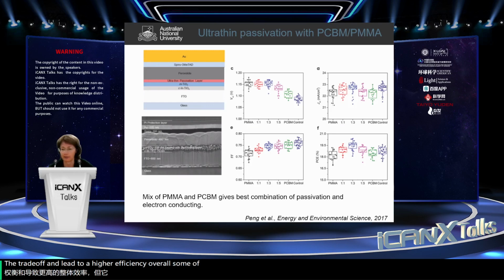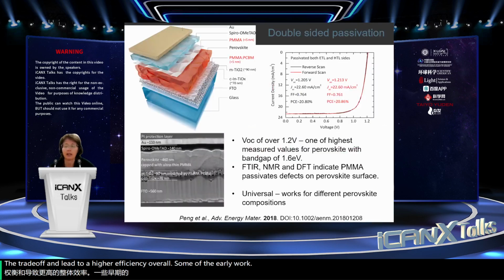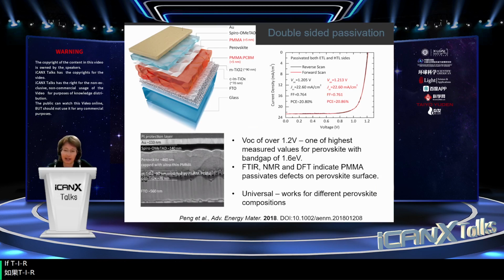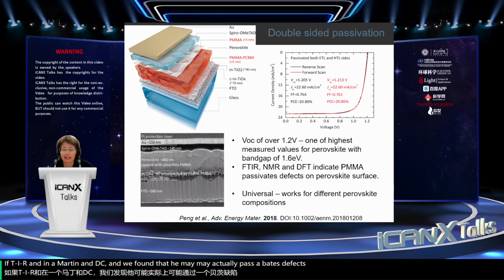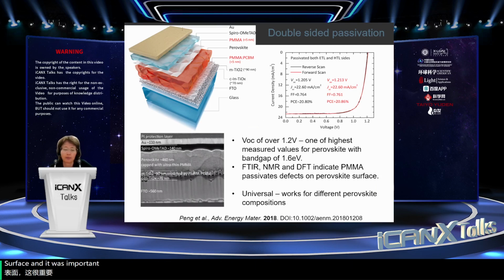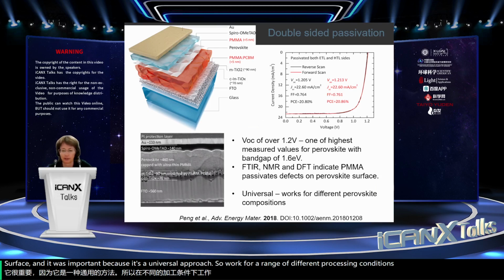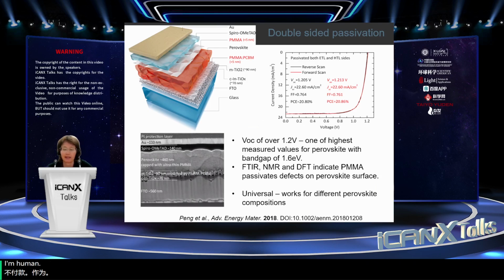So this is some of the early work. We then applied passivation to both sides of the solar cell, and that was a high voltage that we achieved at that time. We did some characterization and computation by FTIR, NMR and DFT, and we found that the PMMA actually passivates defects on the perovskite surface. This was important because it's a universal approach, so it works for a range of different perovskite compositions. Having that PMMA passivation layer is very useful because often you're changing the perovskite composition, for example, to tune the band gap of the solar cell.